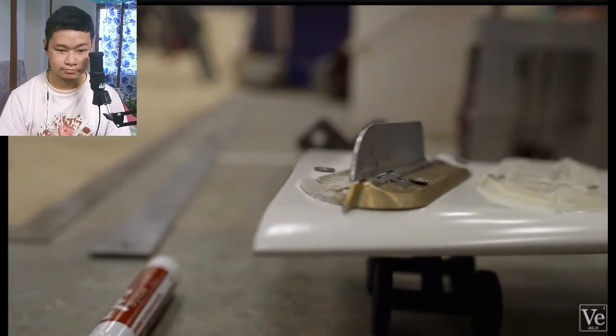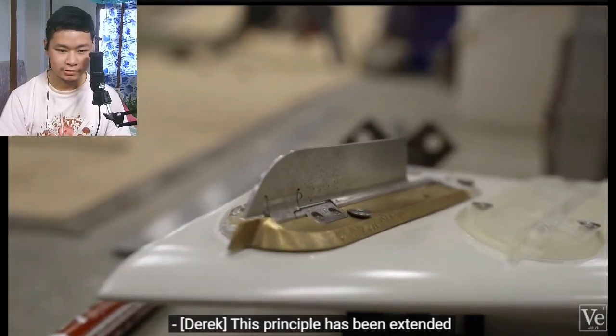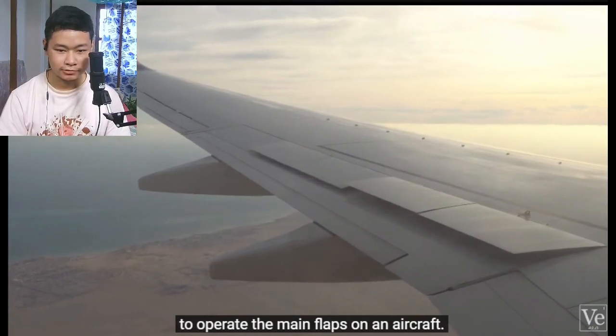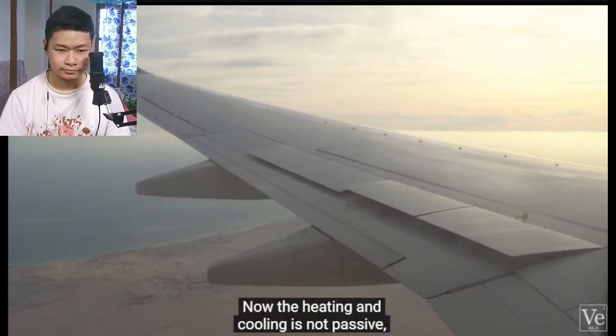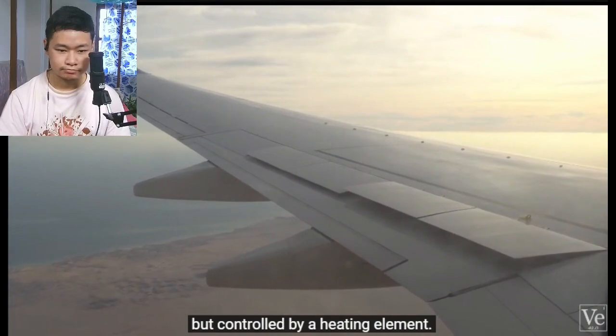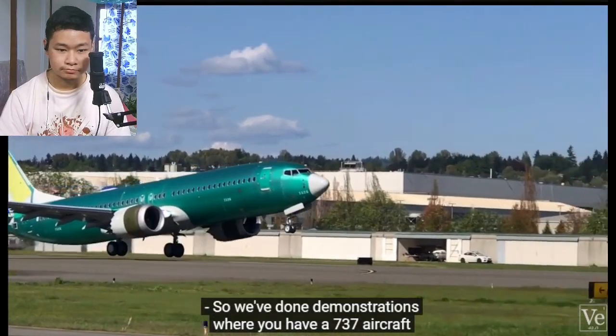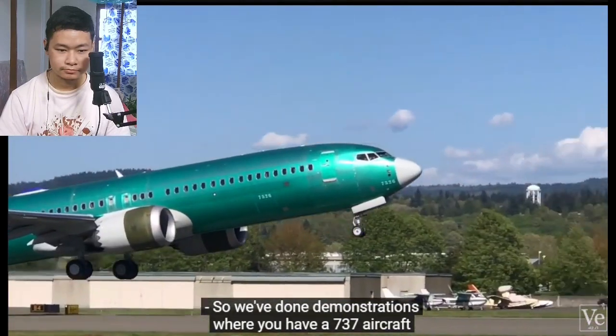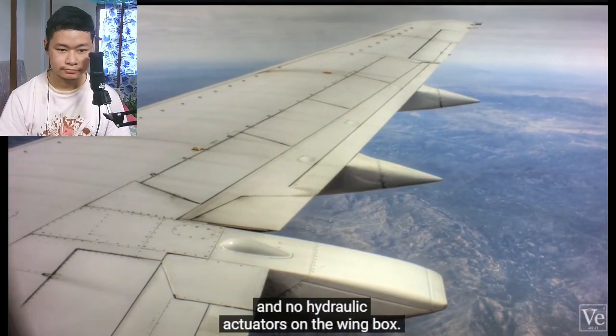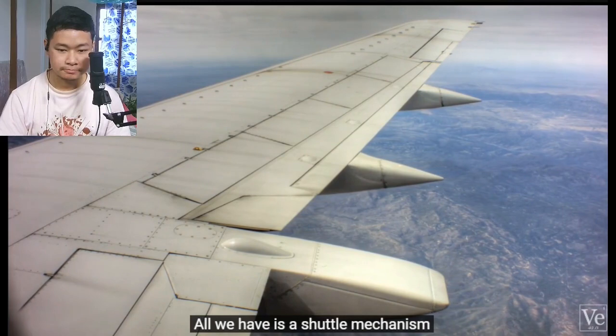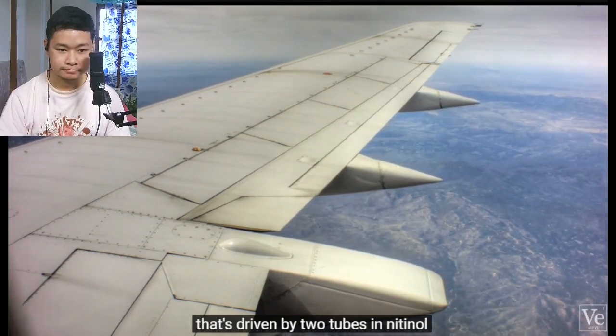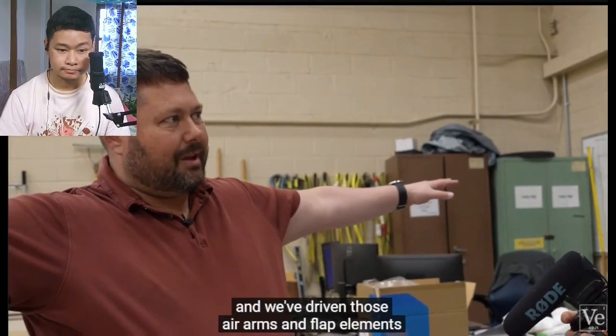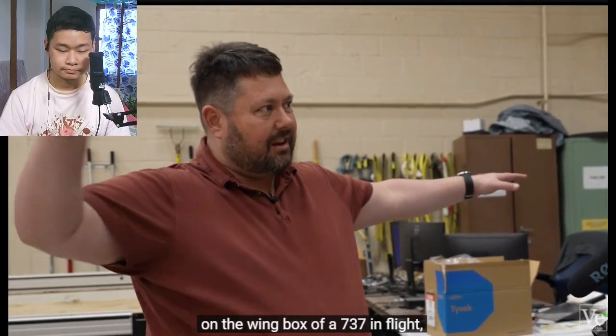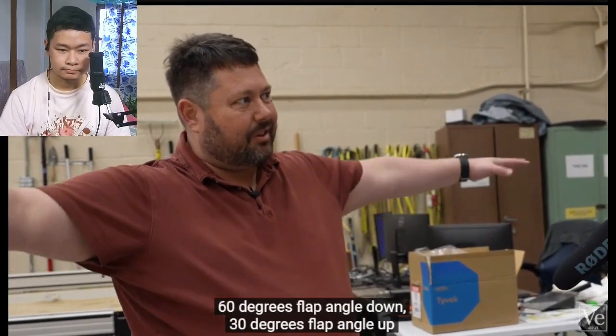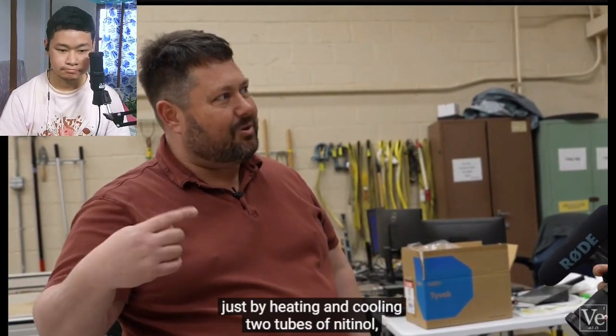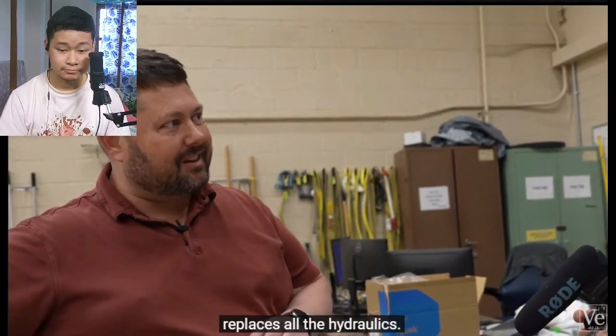it comes right back up. This principle has been used to operate the main flaps on an aircraft. Now, the heating and cooling is not passive, but controlled by a heating element. So we've done demonstrations where you have a 737 aircraft and no hydraulic actuators on the wing box. All we have is a shuttle mechanism that's driven by 2 tubes of nitinol, and we've driven those ailerons and flap elements on the wing box of a 737 in flight, 60 degrees flap angle down, 30 degrees flap angle up, just by heating and cooling 2 tubes of nitinol. Replaces all the hydraulics.